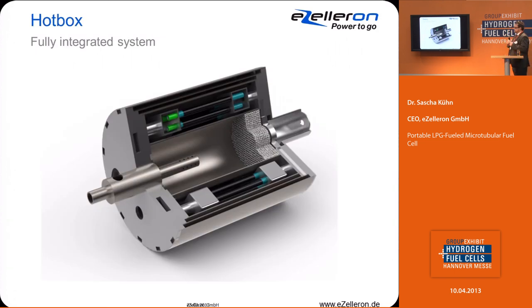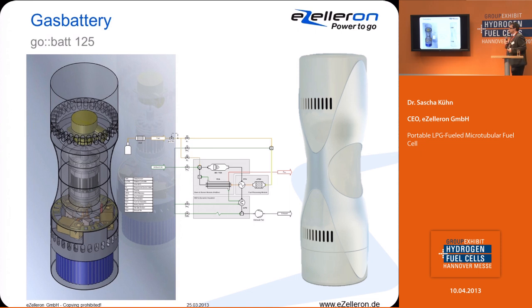The next thing we have to do is to integrate the whole thing into a hot box. So there's a start burner inside, an afterburner, and a pre-reformer, and the whole gases come through connector plates into the inner side of the stack and go through the tubes and then to the afterburner. And we have a heat exchanger on the outside. So in a gas battery, this hot box is only one small part in the middle. There is isolation around it, and on the bottom you can see a gas cartridge, standard camping gas, and several valves, and we have a pump and buffer batteries included into the system.